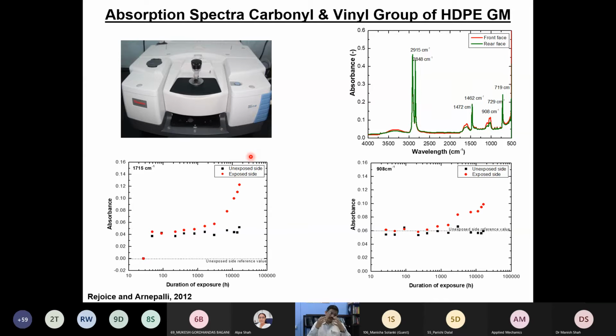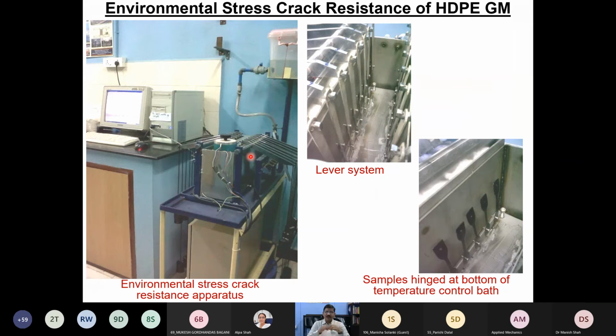Why I'm trying to explain this is, once polymers degrade over a period of time, the polymer initially has certain functional groups, for example in polyethylene, the CH functional group is more predominant. Upon degradation, the carbonyl group becomes more dominant. When the carbonyl group is becoming more dominant, that means aging of the polymer is taking place. There is a term called carbonyl index. We can use this parameter to capture the degree of aging. So we tried to quantify that in terms of FTIR.